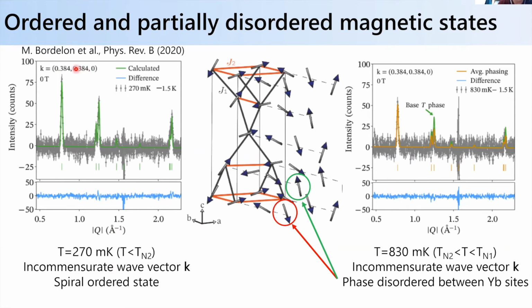It's a helical state. And it's a helical state that's comprised of two different ytterbium sublattices propagating in a helix kind of along these dashed line directions, okay? And there's a relative phase between these two in the ordered state, okay? You can see one helix is sort of anti-parallel to the other as they rotate along, all right?